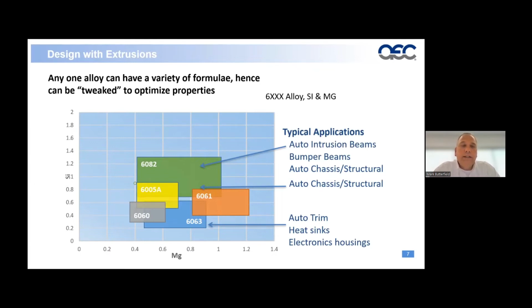One, as we rise in silicon and mag, we also decrease our extrudability, so costs rise. As we increase in both elements, we also demand a higher or more aggressive quench rate that can have a negative impact on tolerances as a result of the distortion during the quench process itself. So understanding the overlap and understanding specifically where your product needs to lie relative to a specific chemistry is a